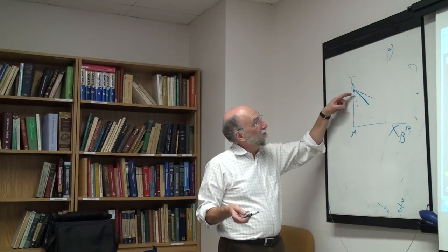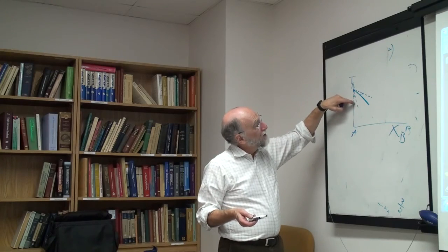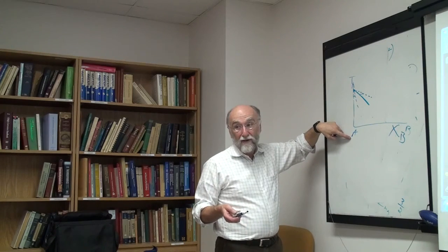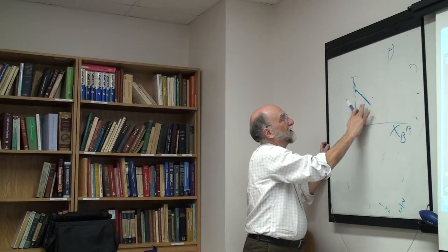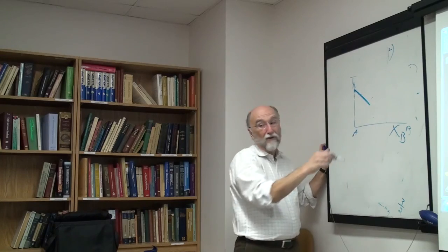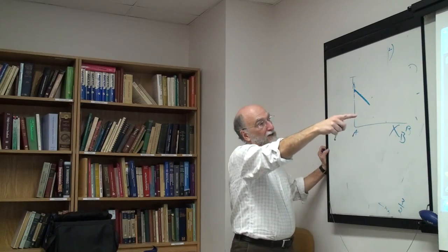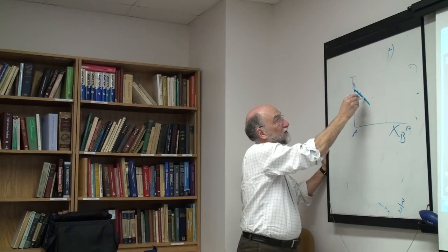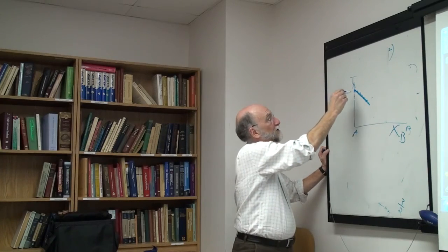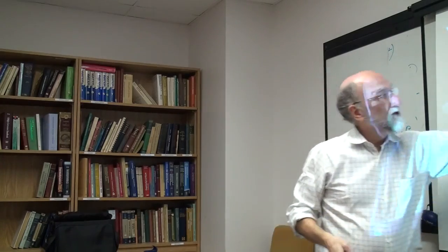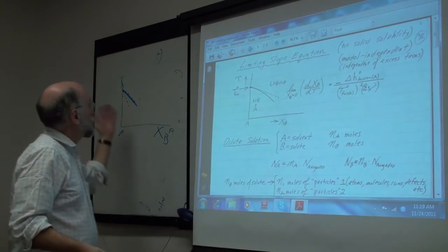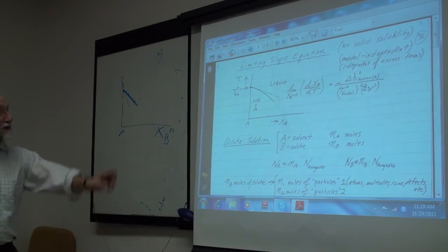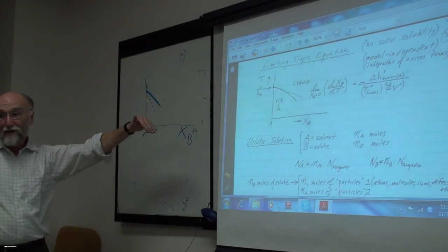Even in this limiting solid solution, it only depends upon the activity of the solvent. If you know the number of foreign particles, and you know the heat of fusion, and you calculate the limiting slope, and this is your experimental liquidus that you've got from the literature, and the limiting slope is below it, and you're sure that your heat of fusion is right, and you're sure that the number of foreign particles is correct, then there's something wrong with the data. For sure there's something wrong with the data. Either the heat of fusion is wrong, or the liquidus has been wrong.